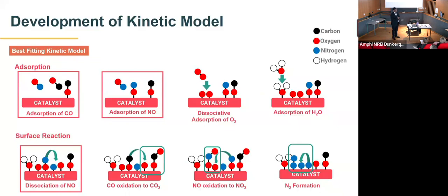So the capability of the surface to act as a reductant in a chemical reaction depends, for instance, on the ratio between copper 1, copper 0, copper 2, or cobalt 2, cobalt 3. This is important when trying to understand what happened during the thermal treatment under controlled atmosphere, what we can call an activation step between synthesis and the normal use of the catalyst.